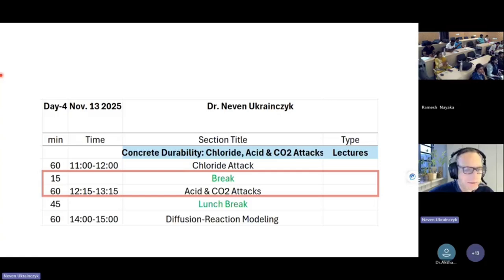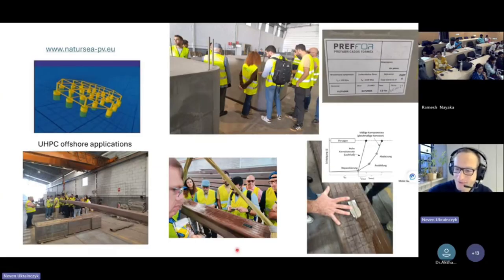RCM is the typical method. But you know what? It doesn't work when you have steel reinforcement. It doesn't work. So how to measure it? Because you need a voltage. You accelerate by voltage, but when you have the steel fibers inside, it disturbs the method. There are some papers actually showing it, but we tried it and it doesn't work. Fundamentally, it cannot be used for measuring the rapid chloride migration coefficient of steel reinforced concrete.